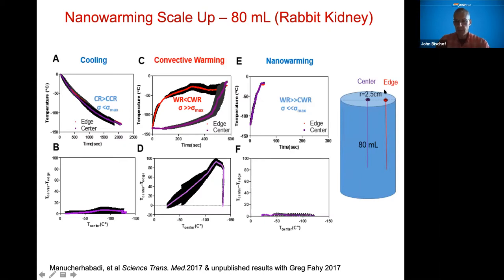And what you see here on the edge and the center, we placed in an 80 ml system a fluoroptic probe. So it's hard to measure in an RF field if you're using thermocouples. So we use fluoroptics. And what we were able to show is that we can cool down in a reproducible way that's greater than that critical cooling rate necessary. Very little thermal, as you go looking down at B, very little difference between the center and the edge. So we can get to the vitrified state just like Greg did back in the 80s.